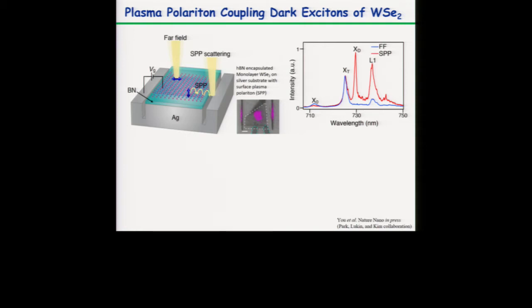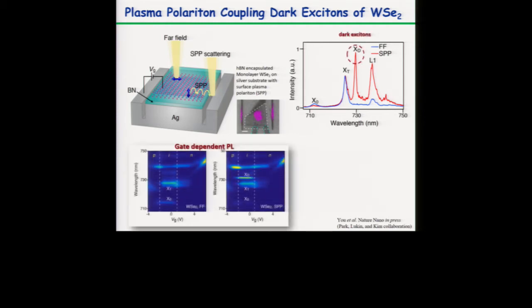But if now we collect away on this grating, away from the excitation spot, we can also obtain PL. But now there is an extra peak. This is the XD, which is a dark exciton. The dark excitons in TMDCs have an out-of-plane polarization, so you cannot observe them in far field. As you see, in the blue plot there is no peak here. But once you couple them to plasmon polaritons, like silver, we can now excite this out-of-plane exciton. I mean, we can now collect them. We can now see this dark exciton, right? This is all in collaboration with the Park and the Lukin group.